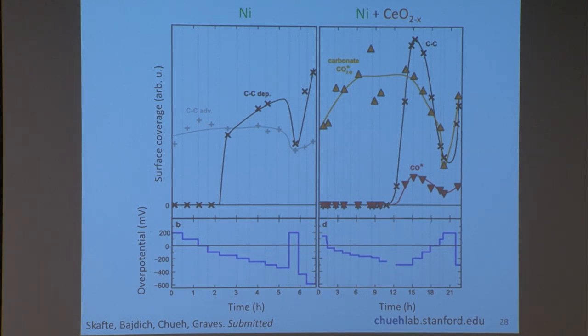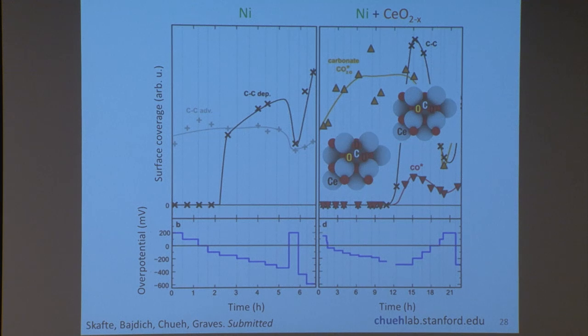CO2-. To visualize this a bit, this is basically a CO3 molecule sitting on the surface, and this is a CO2 molecule sitting on the surface of this material. And what I'm going to show you is where this sits, there has to be a missing oxygen to begin with. Without the missing oxygen, none of these happen. And the reason why these species are important is when they're present, the carbon deposition is avoided.